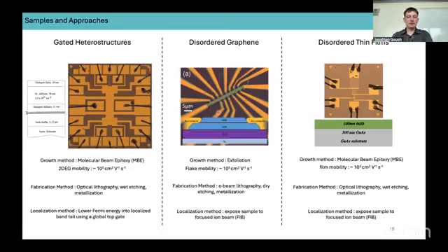So rather than using gated structures, we then introduce disorder using a variety of methods. One is with doping, but a more successful method was with exposure to a focused ion beam. This is how we studied the properties of disordered graphene, as well as disordered indium antimonide thin films. Typically our films are grown by molecular beam epitaxy. They're typically either 20 nanometers to 300 nanometers. We're limited on the thickness of these films due to the growth properties. They tend to grow in clumps if you try and make a film less than 20 nanometers.